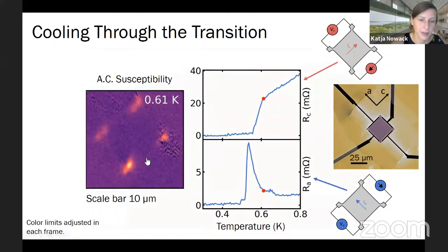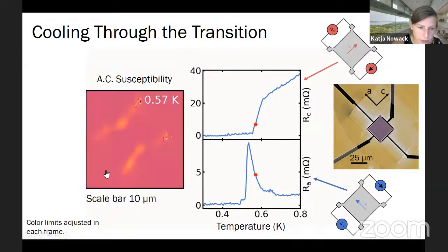So now we can actually look at the superconductivity in the sample as we cool through the superconducting transition. Okay, let's hope this movie actually plays. Yes, here we go. So we start at high temperature and then cool down. And you just saw that there are already some little puddles forming in the four corners of the device. I should point out that the frame you're looking at is a zoom in on the device right here. Let's go a little bit further in temperature.